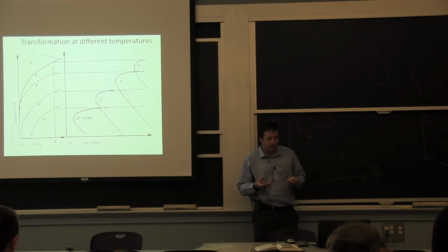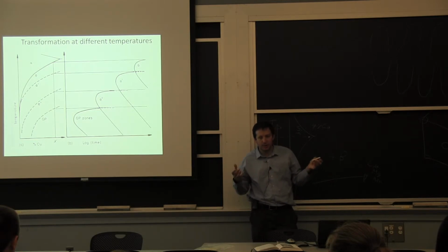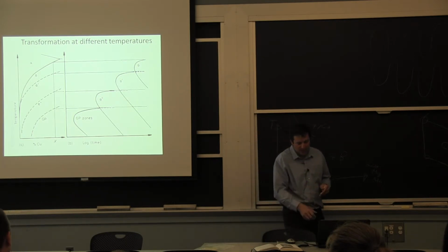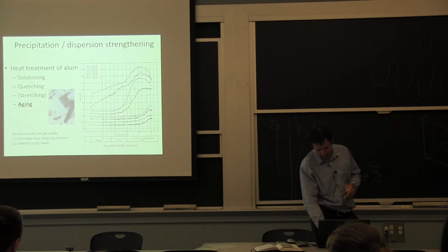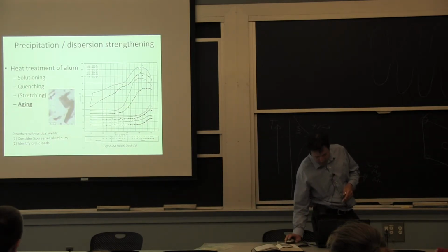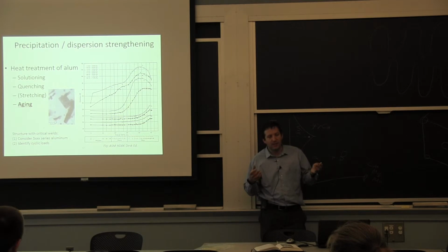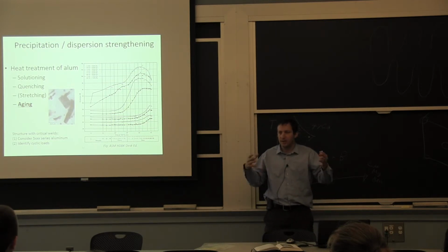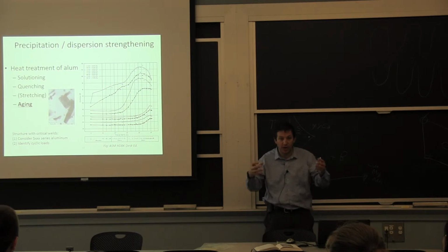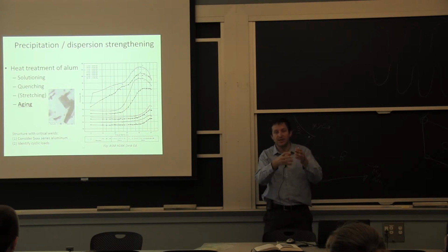At very low temperature, you don't have a lot of thermal excitation, you don't have much diffusion, so you're going to need to have a very small, stable nucleus. Very small and stable means that it's coherent. And I've shown some images. These are TEM images, so you're looking only at 500 nanometers here. You're forming very, very fine precipitates in your structure, and you didn't create the interface. It's just a form of segregation. If it used to be the same composition everywhere, now all of a sudden you have a little more of it in this area, but it's still coherent with the base structure.